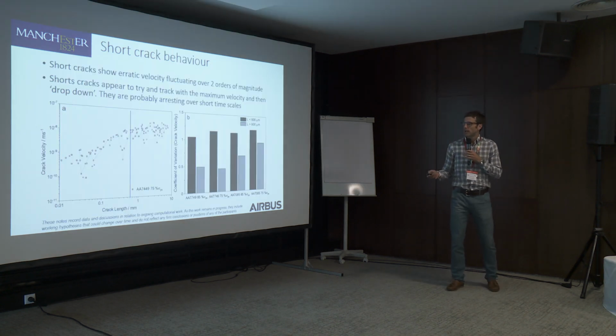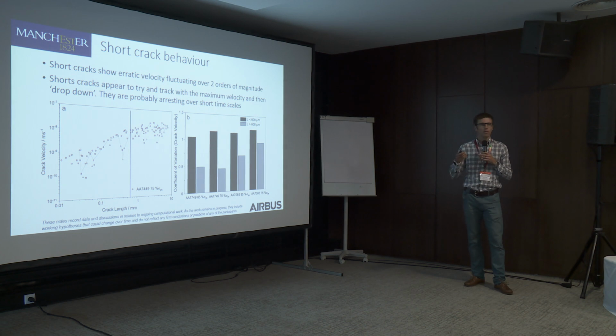So just now I'm going to try and pull together the mechanical information that we've got, and the observations of the cracks, with what we've seen in the microstructure of the material. And one of the first things that we can see is that we have a consistently different behavior between the short cracks and the long cracks.